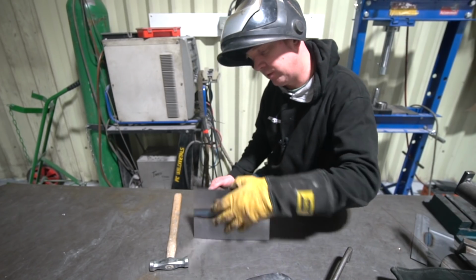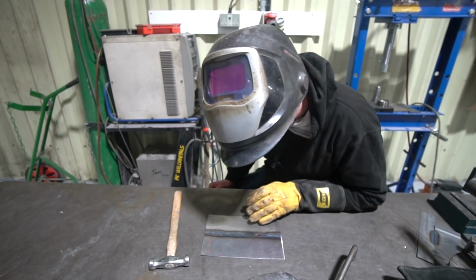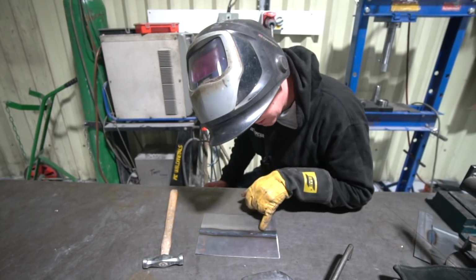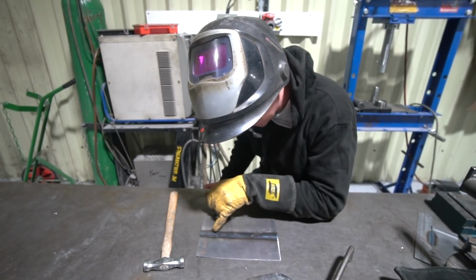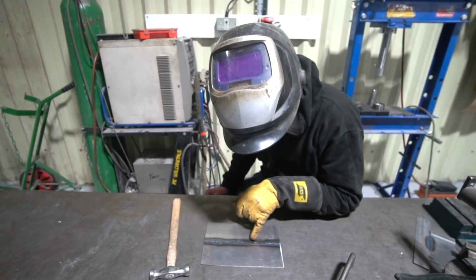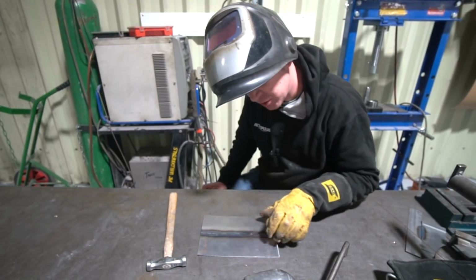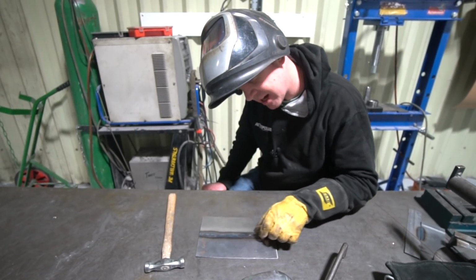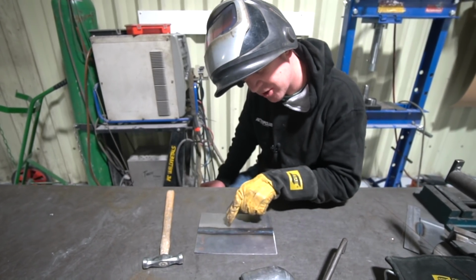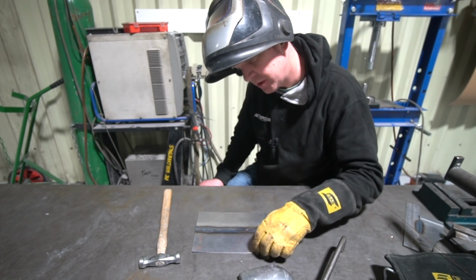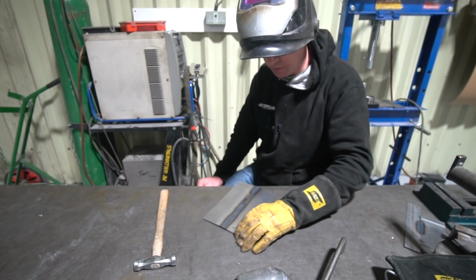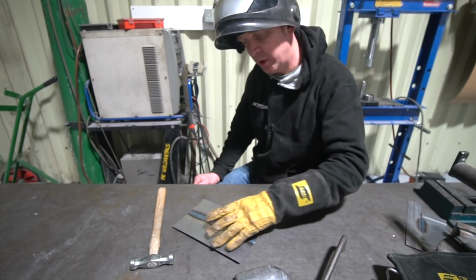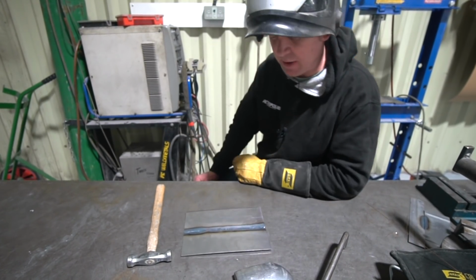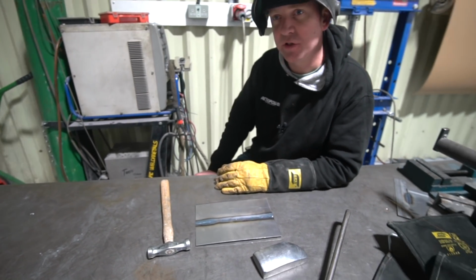So you've got to let that cool down a bit. Just turn it over while we're waiting to do that. You can see it's pulled up a little bit. You can see that there's some weld dropout along most of the way along the back, a little bit light there. I probably didn't have quite enough heat there. Which is interesting. You can see where that's gone narrow, exactly at the point where it's only just dropping through. So you can see though that that's a pretty reasonable weld, and that's how we would do nearly all of our patch repairs on external surfaces of the car.